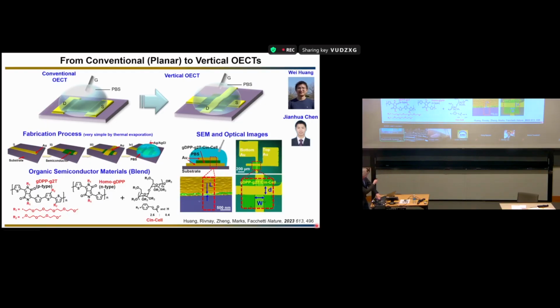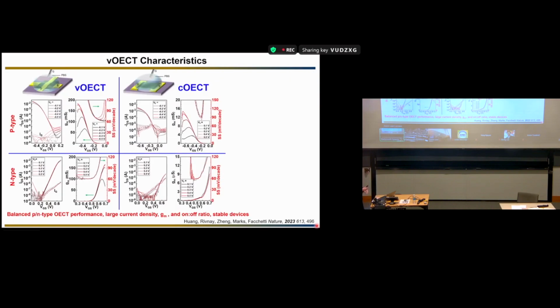To demonstrate the concept, we use two organic semiconductors. This is a P-type semiconductor to transport positive carriers, and this is an N-type semiconductor to transport negative carriers. And this device also works quite well. It was not obvious when we started. These are the devices in the vertical architecture, and this is the control device with the conventional architecture. This is for the P-type semiconductor: if you compare this current with the conventional one, you see the current is much larger, an amplification. For the N-type, this is the current, and this is the current for the conventional device, much larger. So it works very, very well.